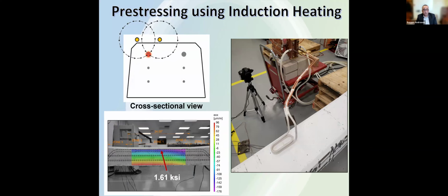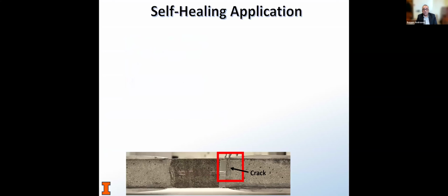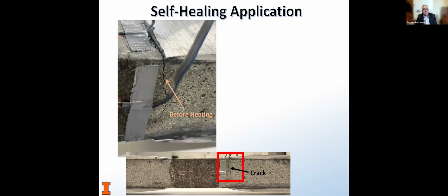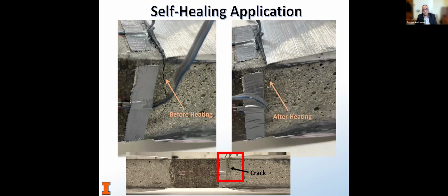The same concept could be applied for self-healing, something that we've been thinking about. There's been a lot of studies about it in other areas, but now with SMA, imagine having something like this, a crack of this size, and you have SMA bars inside. Whether it's pre-stressed or not, if you heat it again, that's what happens. This is exactly a specimen with SMA inside, and we heated the SMA. And some of you might not even see where the crack is. And that, of course, will help in improving significantly the durability of concrete. So our group will be giving a talk next month also at the ASCE Structures Congress in Phoenix about these self-healing applications and research we've been doing with SMAs.